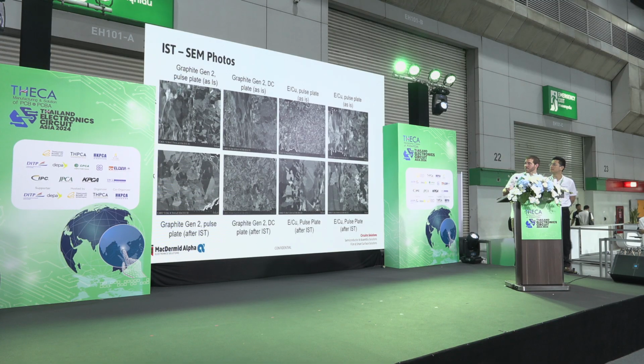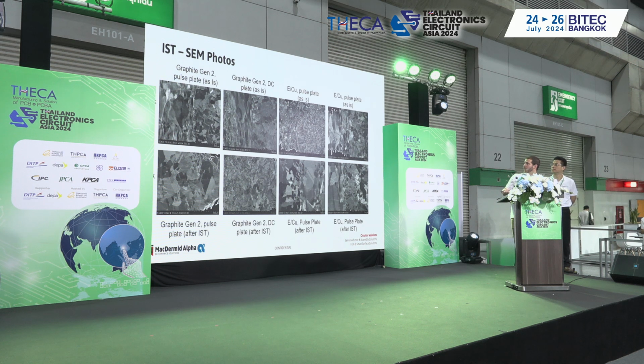We have some additional IST photos just showing examples of the graphite Gen 2 with pulse, the graphite Gen 2 with the DC. You can see the difference in grain structure, the electroless copper with pulse, and the electroless copper with DC, to show the comparison of the grain structures between the various conditions before and after IST performance.